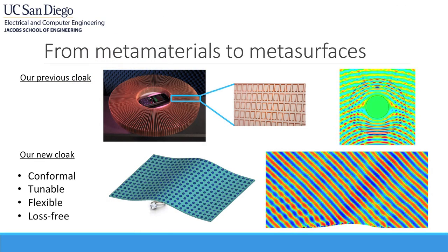Previously, people were using very bulky systems in order to cloak a device or an object, and the cloak itself was bigger than the object being cloaked. Recently, we have transposed that system to an ultra-thin surface — using a simple thin sheet of dielectric particles, you are able to make an object disappear. It is important to use lossless dielectric particles, because if you use a lossy material, it will absorb light and create a contrast in brightness, which would be very suspicious. So it is of utmost importance to use lossless systems for cloaking.